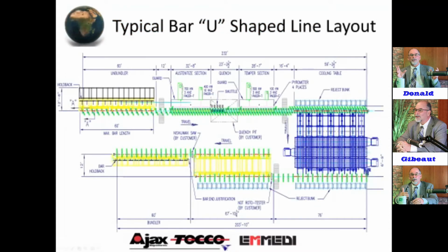Here's another line, how it looks, typically a U-shaped layout. These items on the cooling bed here are what we call forced air convection fan systems. On the cooling bed, you can austenitize, quench, and temper, and then it comes onto this cooling bed. For the first half, till the product gets cooled down to about 600 degrees in open air, you want to keep a rotation, and it has to just cool down in open air naturally. But after that 600 degree point, you can pour the coals to it. So we have these forced air convection fan systems that go underneath the cooling bed that can aid in cooling